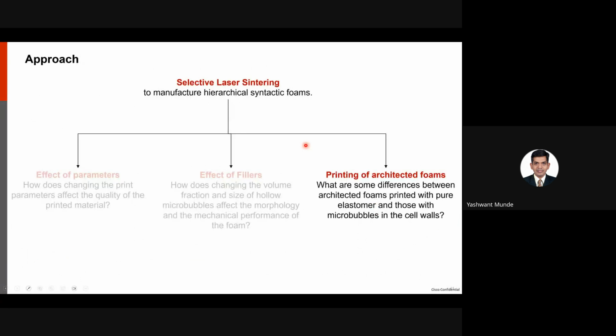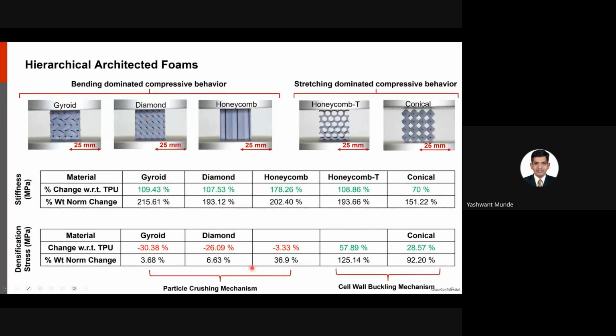So the last one is how this difference in stiffness and densification manifests in the architected cores. Before that, we consider two types of architected foams. One is bending dominated and the other is stretching dominated. In the bending dominated ones, which are gyroid, diamond, and honeycomb, the main mechanism is the walls of these architectures come in contact, compress, and cause collapse of particles.